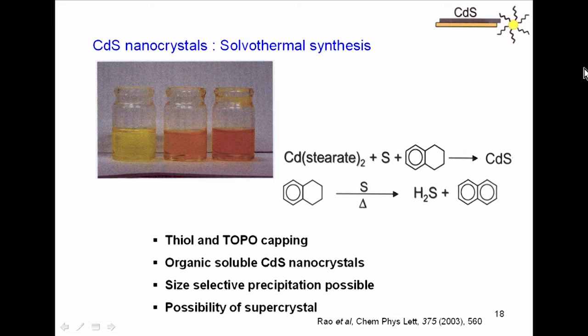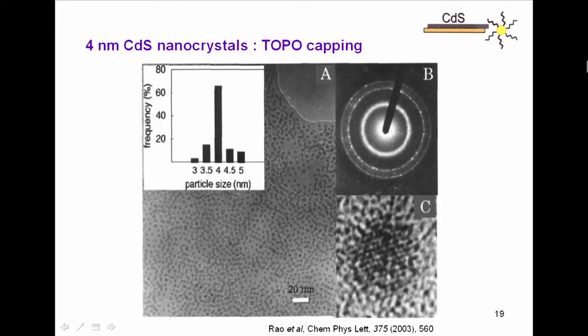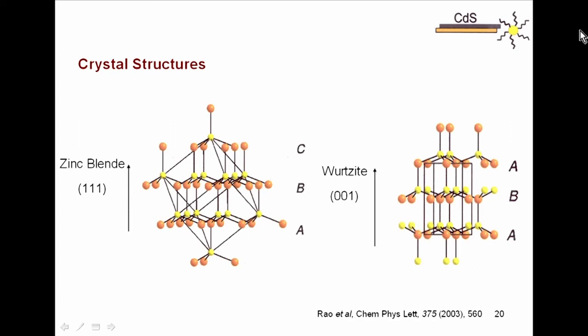What one normally does, once it is made, is electron microscopy. You can see on the bottom right-hand side one particle of cadmium sulfide, where you see the lattice planes, and so it is a single crystal. Each particle is a single crystal. You can study all the particles. You can then study structure. And one of the nice things about nanoscience is when the particle size is small, you get metastable structures quite often. You don't get the more thermodynamically stable structure. And a lot of studies have been made in this direction.